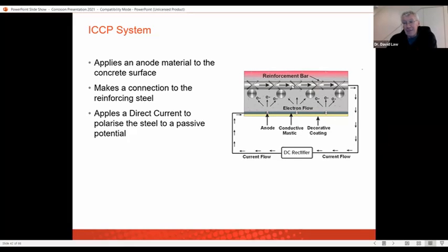And this means that your chloride ions are to a degree repelled from your steel, and you're generating hydroxyl ions at the surface. So these are what are termed the secondary effects. So what you're doing when you apply it, you're polarizing the steel into that immune area that I talked about at the beginning by reducing the potential to around -1100, -1200 millivolts. But you also have this secondary effect.